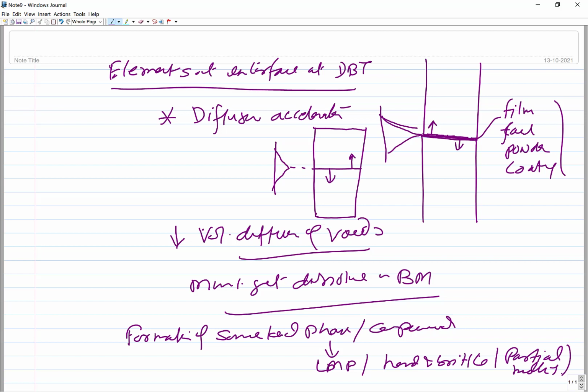So all these undesirable things can be there if the diffusion accelerators are not dissolving and distributing, getting homogenized near the interface properly, and these are forming some kind of phases, intermetallic compounds, leading to the undesirable effects of these phases in form of low melting point, hard and brittle, and partial melting. So these can be especially problematic for the joint performance. Okay, so it is very important that the desired diffusion activators or accelerators to be added at the interface are selected properly.